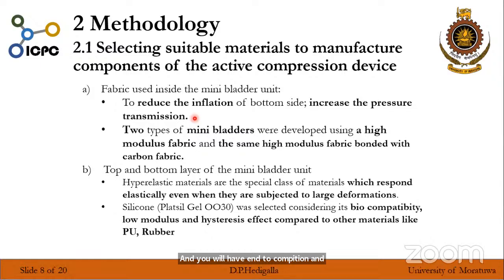The active compression device was developed with 3 layers: top, bottom, and the fabric layer. Here the fabric layer was introduced into this active compression device to reduce the inflation of the bottom side, such that we can increase the pressure transmission percentage. So there are 2 mini bladders developed using high modulus fabric, and the same high modulus fabric bonded with the carbon fabric. The top and bottom layers of the mini bladder unit were developed using hyperelastic materials like silicone, based on its biocompatibility, low modulus, and hysteresis effect compared to other materials like rubber and PU.